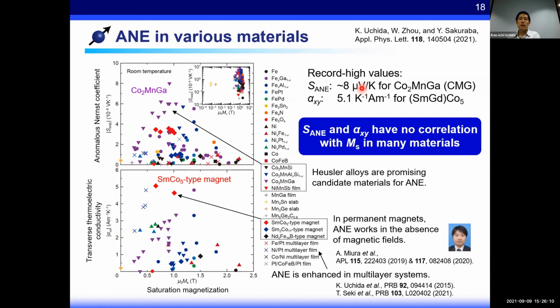These graphs show the anomalous Nernst coefficient and transverse thermoelectric conductivity for various magnetic materials reported so far. The coefficient is often compared in terms of field-dependent magnetization rather than the saturation magnetization. However, since the anomalous Nernst effect and related transport properties are estimated for uniformly magnetized materials, it's natural to compare the coefficient in terms of saturation magnetization, not simple magnetization.